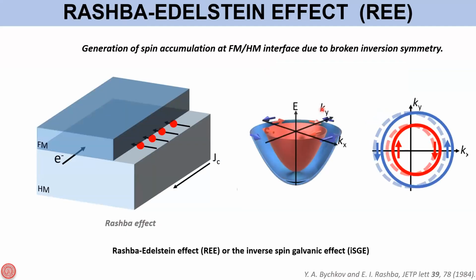Another effect which can also lead to spin orbit torque is the so-called Rashba-Edelstein effect. This Rashba-Edelstein effect arises from the interface between, for example, a ferromagnet and a heavy metal. There is a broken inversion symmetry, and this leads to spin splitting of the band and spin momentum locking, and a band structure which looks like this. Consequently, when you apply current, the Fermi contour will shift in a manner that will generate a spin accumulation.